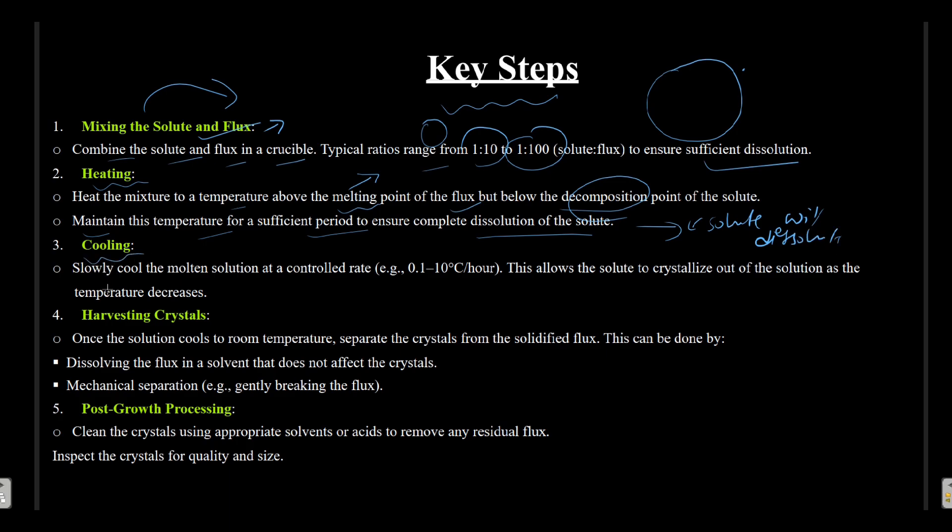Now the third step is cooling. So slowly cool the molten solution at a controlled rate. So slowly the molten solution is cooled. You can see over here 0.1 to 10 degrees Celsius per hour. The cooling speed should be very low.